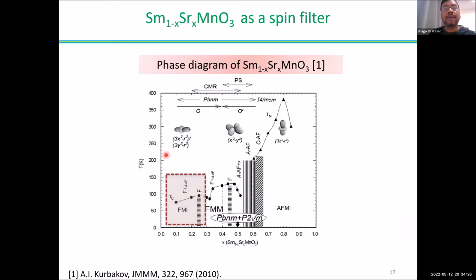So I have used samarium strontium manganese oxide, which is a manganite system, and this is the phase diagram of this material system. What you see here is that in the low doping regime, below 0.3, this is actually a ferromagnetic insulating system. Somewhere around 0.25, you have a single ferromagnetic insulating phase. So this is what I have used, samarium 0.75 strontium 0.25 MnO3, which we can call SSMO from here onward. This is the particular ferromagnetic insulating phase that I have used for our devices.